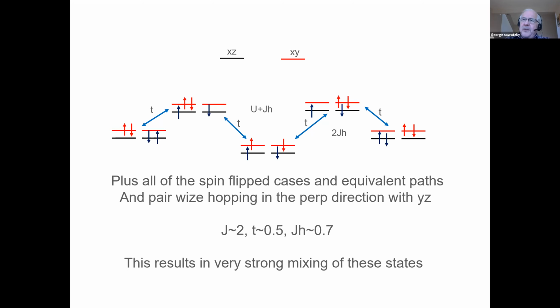So the STO that is used, and that was this double layer I was talking about. What they do in order to get rid of the oxygen vacancies as much as possible is they heat it up to around 900 degrees Kelvin in oxygen. And that removes the oxygen vacancies. But what it also does is it removes some strontium from the first layer. And you then get an STO which is basically almost pure, with a double TiO2 layer. But it doesn't have the same structure as the terminating TiO2 layer of STO. It has a complicated structure. These are these beautiful results of the surface truncation rod experiments by Clejou and who was it?